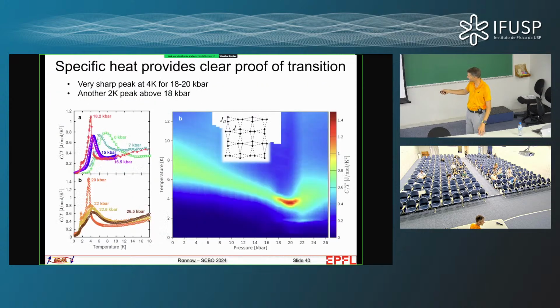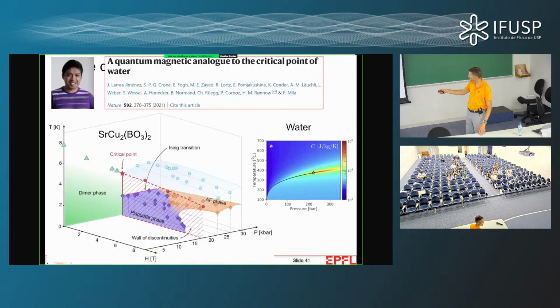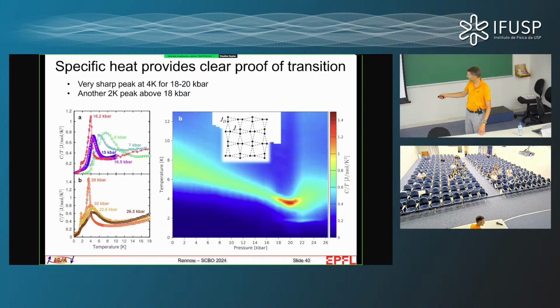So essentially, we do not see the critical line itself. One of the reasons we do not see it is because the direction in which Julio is scanning is like this. We never scan across at fixed temperature, scanning the pressure. Since in water the phase boundary has a slope, regardless of whether you scan temperature at fixed pressure or pressure at fixed temperature, you cross the phase boundary. Here, you would have to have fixed temperature and scan pressure.